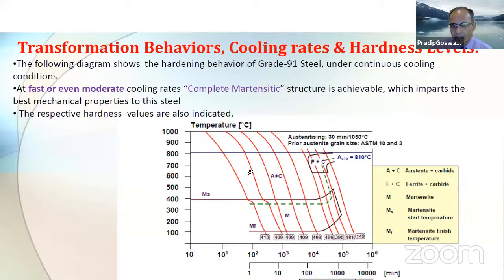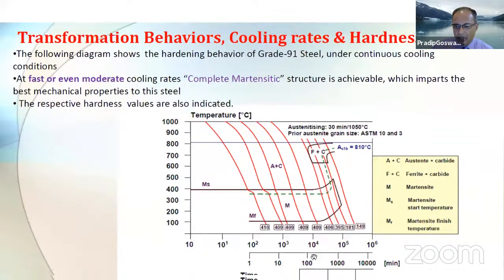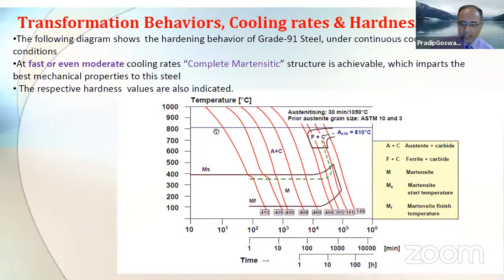graph, the vertical line is the temperature, and the horizontal line is the typical cooling rates. Here you see faster cooling, and you go on to slower cooling because you are increasing the time allowed for cooling. So with the faster cooling time, generally speaking, you are able to get martensitic structures at room temperature. And when you go for slower cooling,